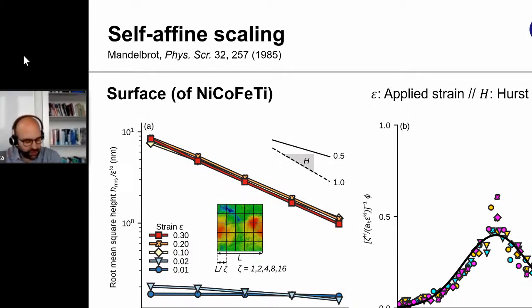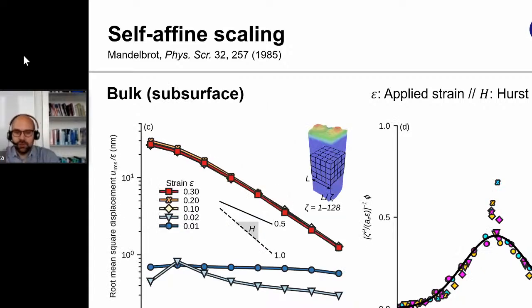There's something else that we can do in these calculations. We cannot just look at the surface, but we can also ask the question, what happens subsurface? So what we've done is exactly the same analysis as on the surface in the subsurface region. We are now asking the question, by how much does an atom move in the direction normal to the surface? If we ask this question at the surface, this gives us a surface topography. In the subsurface, it gives us a measure for the deformation profile.